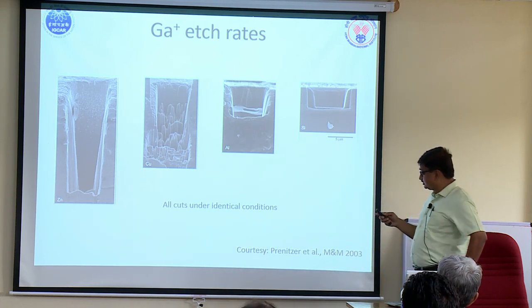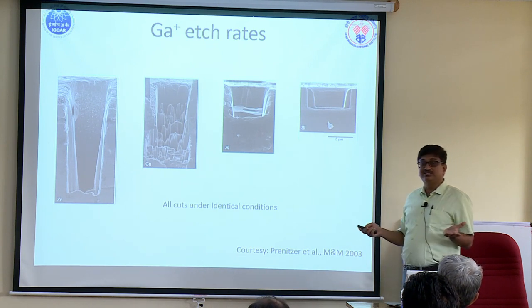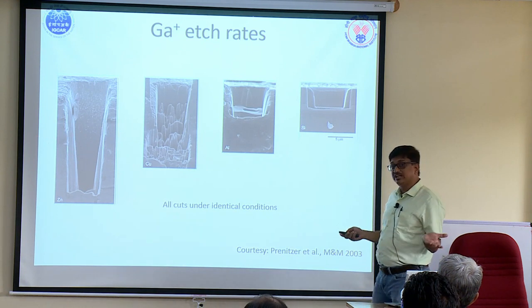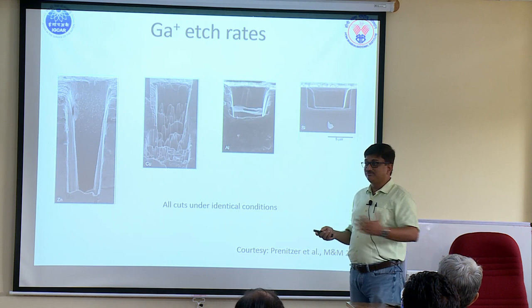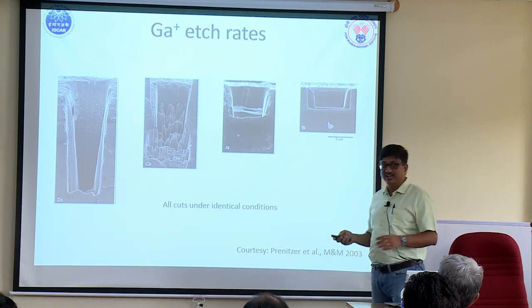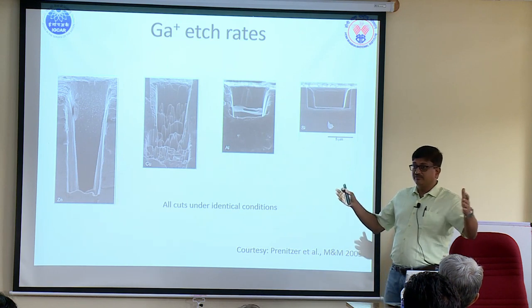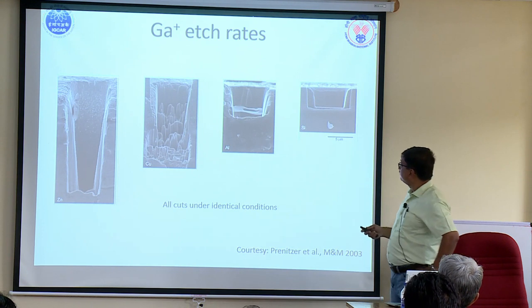But whatever it is, you will still have this kind of structure. That is the copper which has been removed. The pump is not efficient enough to suck it away, so it gets redeposited, and you always start getting that. If you look at it at even lower magnification, it looks like curtains, and they always call it the curtaining effect.